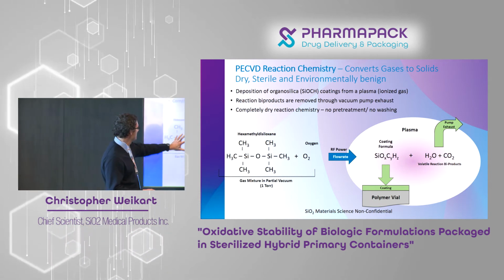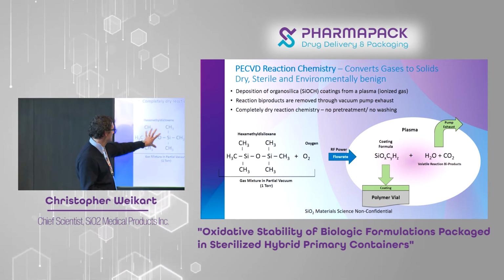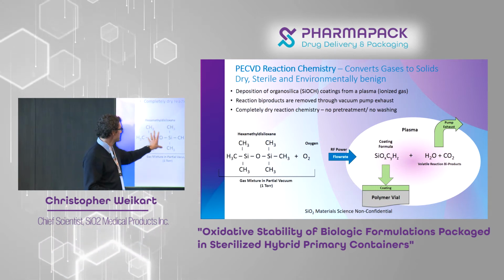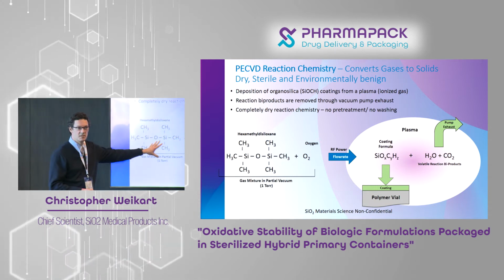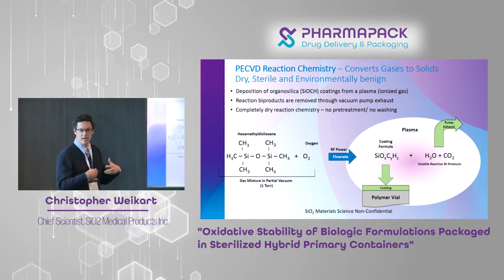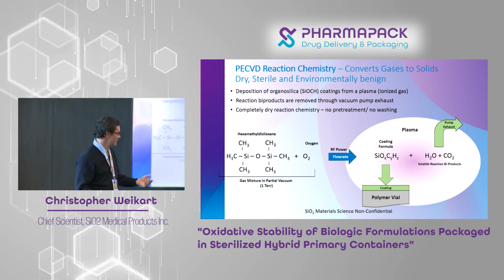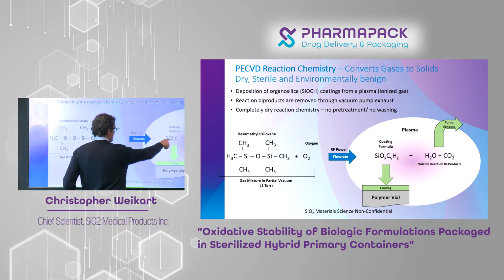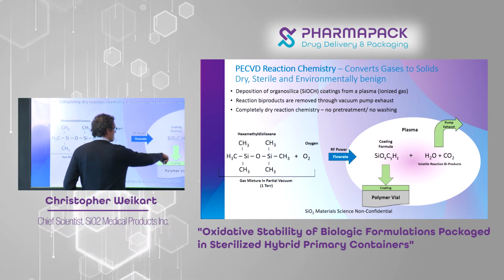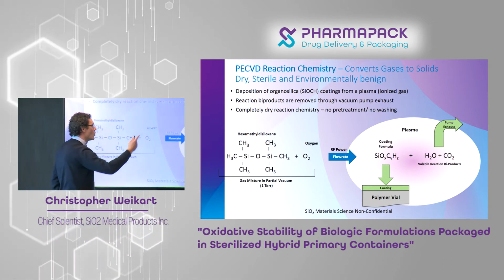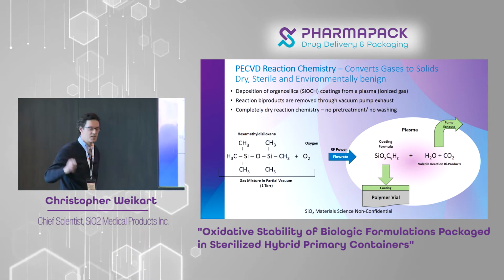This gives you an idea of the sort of chemistry. This is actually a liquid at room temperature. We deliver this as a vapor, mix it with oxygen at very low pressure. And then, of course, we form the plasma to produce a coating. This is a silica-based coating. In this case, it's got a little bit of carbon in there. And you get residual gases like water and CO2 that go through the vacuum system.